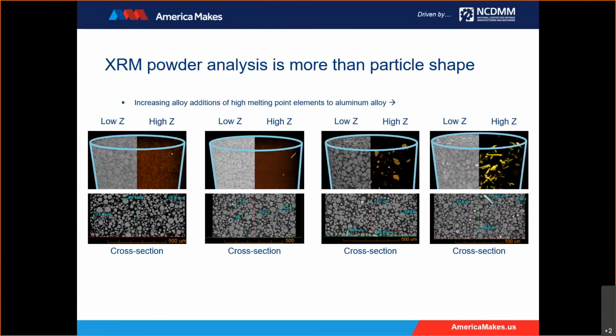Here we're looking at an alloy development project where the researchers at Oak Ridge National Lab are using thermodynamic models to design new aluminum alloys. We're looking at 4 different samples with increasing alloying elements being added from left to right. At the top, we have a 3D volume that's split into 2 regions to show low atomic contrast elements on the left and high Z contrast elements on the right of each volume. If we take a look at the low Z region, they look pretty homogeneous. But on the right-hand side, we can see some differences in the high Z contrast region.